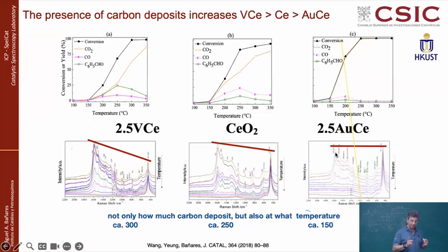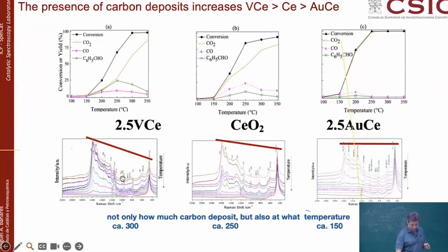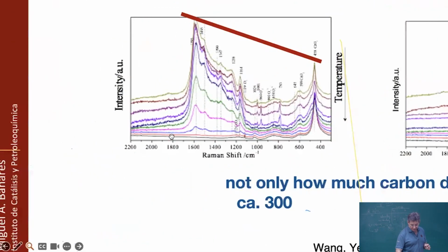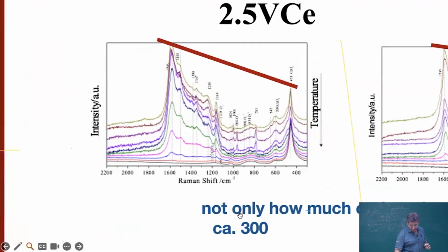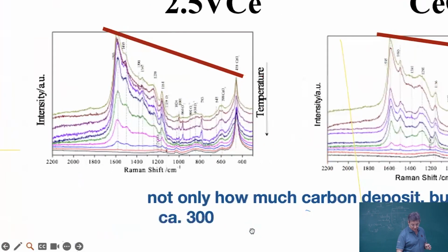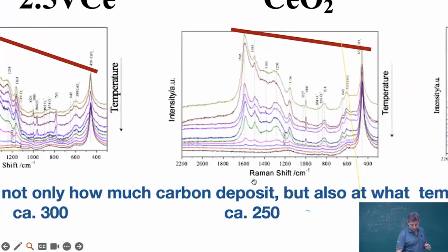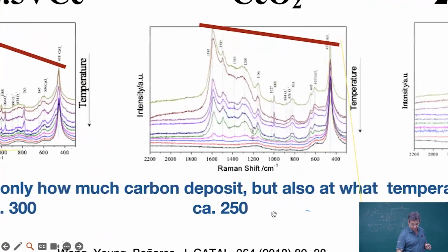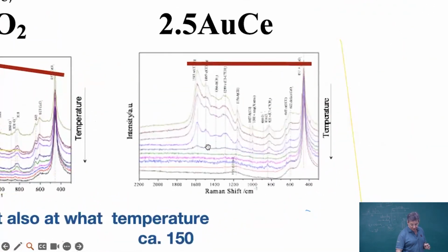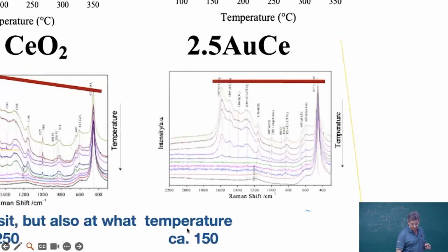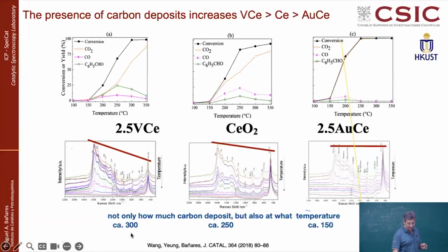This is very qualitative. But what is more informative is at what temperature you are getting rid of these carbon deposits. If you look down here, you are getting rid of carbon deposits basically at about 300 degrees. On ceria, you are getting rid of the carbon deposit at about 250. And in gold ceria, you are getting rid of the carbon deposits at about 150. So there is a dramatic difference if you are getting rid of carbon deposits at the surface of this catalyst at 300, 250, or 150.